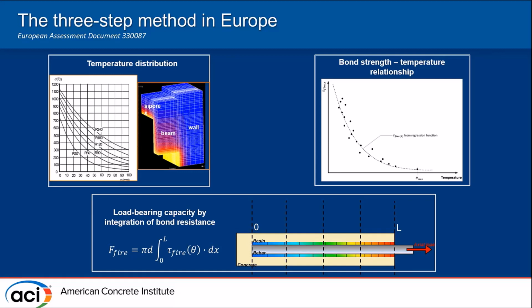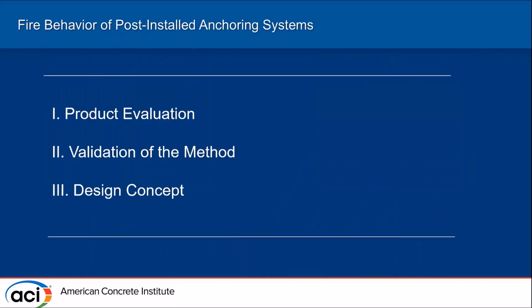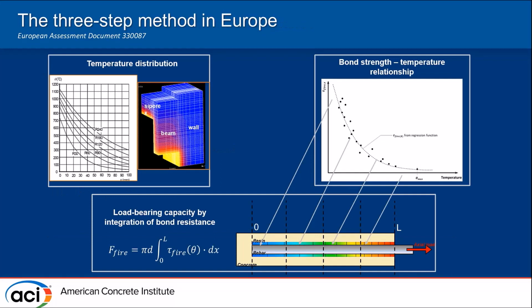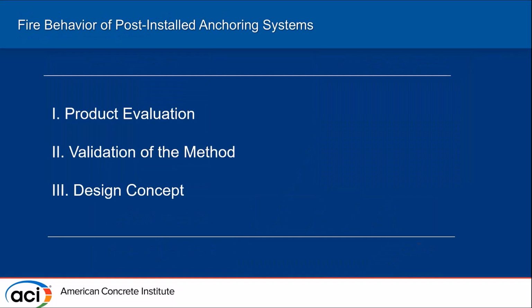And finally, in the last step, knowing the temperatures and this relationship, we can associate a given bond strength to each segment along the bond, and then integrate along the entire length in order to get the load bearing capacity at a given time during the fire. And this load bearing capacity is then compared to the demand, to the applied load, in order to know if collapse occurs or not. So in the next parts of this presentation, we're going to start by presenting how we achieve this curve, the second step, which is basically product evaluation. Then we'll present the method that is used and how we validated this method with full-scale tests, and then we'll finish up with the design concept.